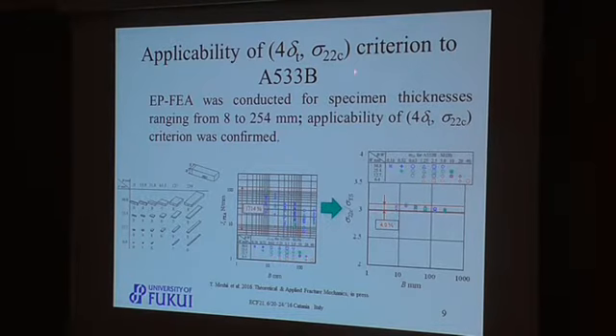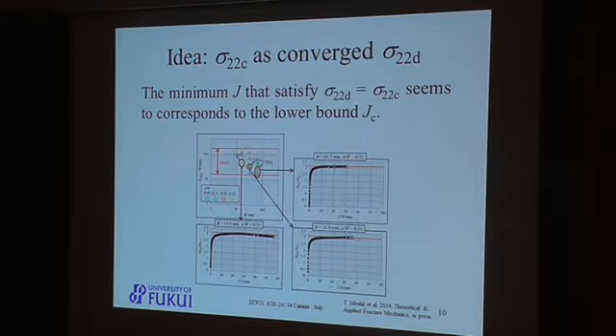Through the examination of the applicability of the 4 times CTOD sigma 22C criterion to the decommissioned reactor pressure vessel steel JC database, with test specimen thicknesses ranging from 8 to 254 millimeters, we reached the idea that the convergence of sigma 22D with increasing load is necessary for fracture initiation, because fracture always occurred after sigma 22D reached sigma 22C. And in addition, the critical value sigma 22C is a converged value of sigma 22D.